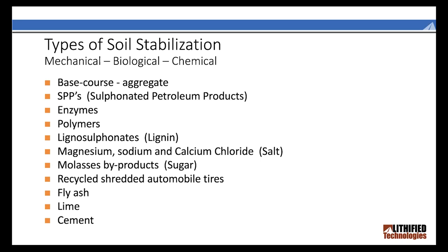Because we can reach the same structural coefficient or the same structural number in your foundation by treating the base and achieving 500,000 PSI modulus, let's say that we treat 8 inches of base course. That is now the same as building your road on top of 8 inches of asphalt. That means you can reduce the pavement design from, say, 4 to 6 inches down to 1.5 or 2 inches, whatever the minimum is the laydown machine can put down on top of that road. And you just saved 50 to 67% of the cost of the asphalt. And the asphalt is the biggest number in the total cost of building a road.